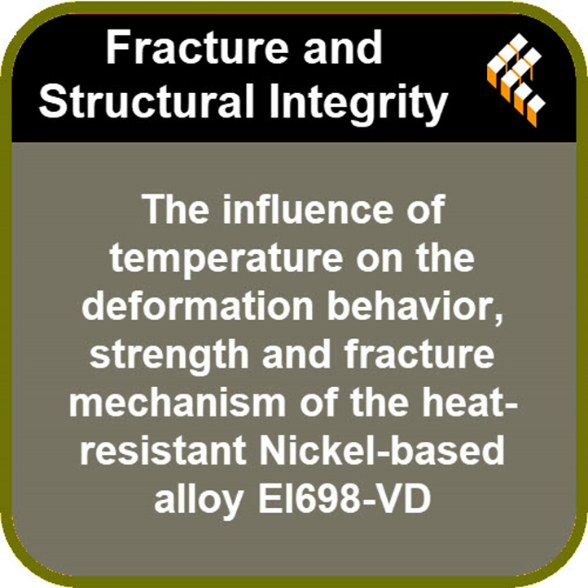So to find the culprit, the researchers ran a pretty standard test. The monotonic tensile test. Right. They took little cylinder-shaped samples of the alloy, put them in a furnace, and heated them up. All the way from room temperature up to 700 degrees C. And then they just pulled them until they broke.